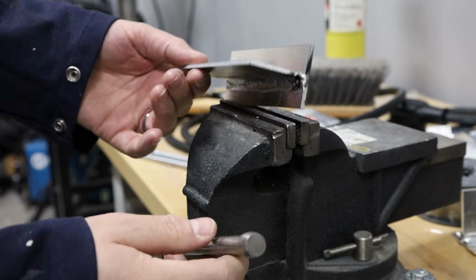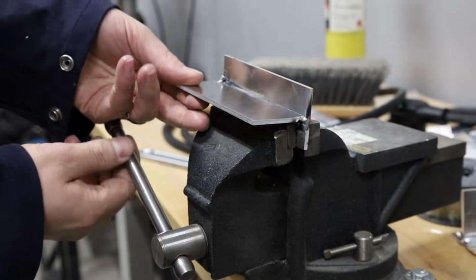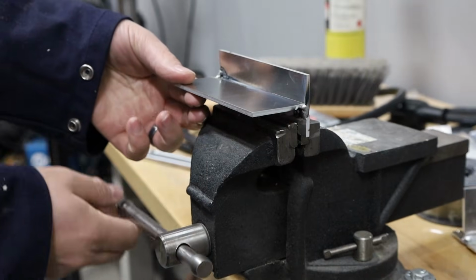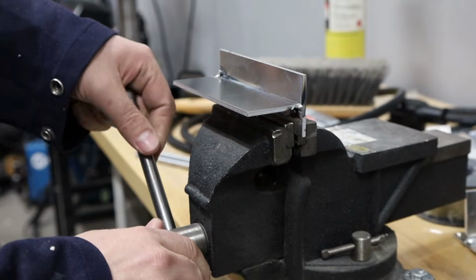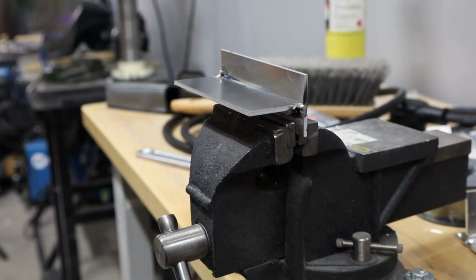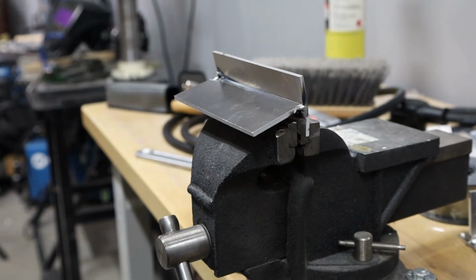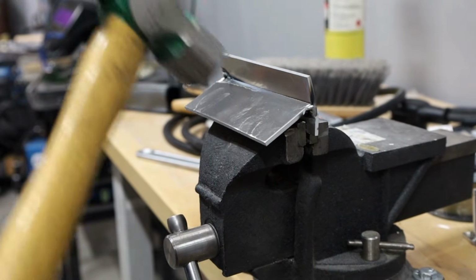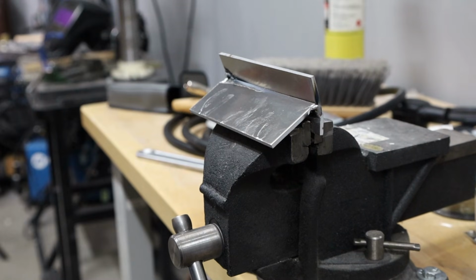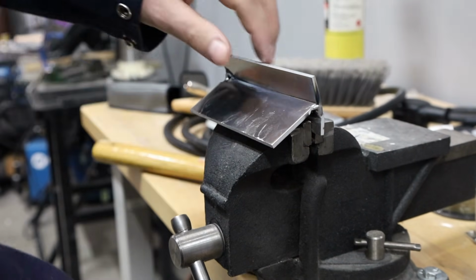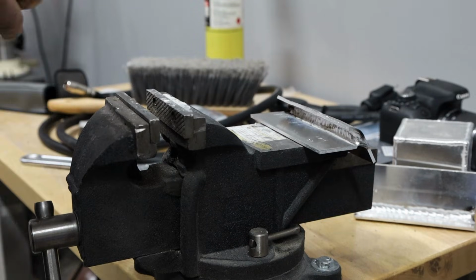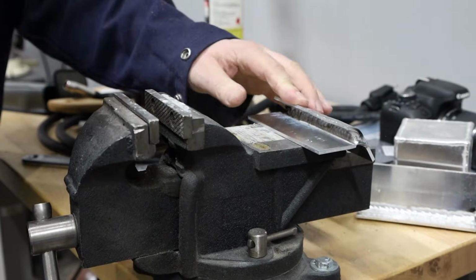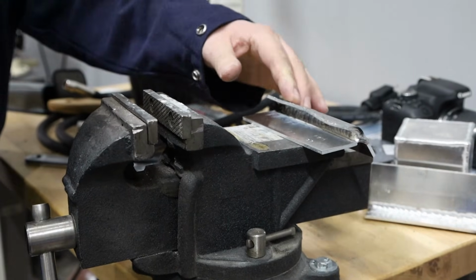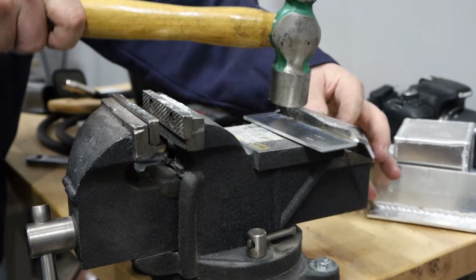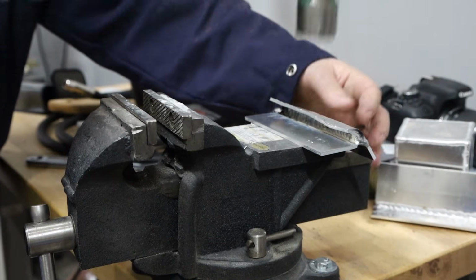And it's good to dial in your settings and your technique by doing some amount of test. And this is a good test to do on a fillet weld, where you just clamp it in a vise and bend it open. And notice how I just welded one side and I'm bending the root open. And this is a much better test than if I were to bend it the other way. It would probably hold up about no matter what you had. It'd have to be really bad to break the other way. But anyway, I'll go ahead and take it. And the idea is to bend these all the way over to each other. And you know, if you don't get all the way there, you still get a pretty good idea of what's going on.